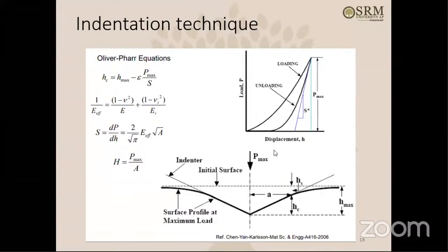Basically, you measure this particular event when the indentation is happening. You measure the load and displacement of that indenter: how the indenter is moving and how the load is varying. This is how it shows. You press the indenter against the surface, it goes down, it reaches the maximum, and then it comes back. Generally, loading and unloading.